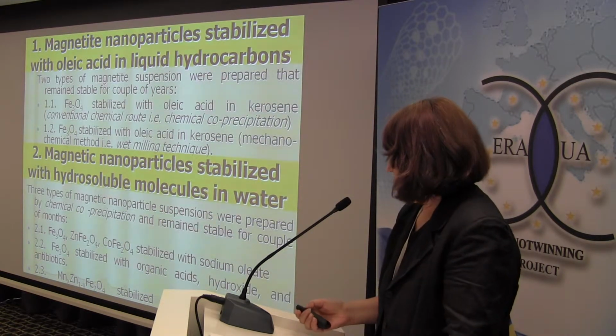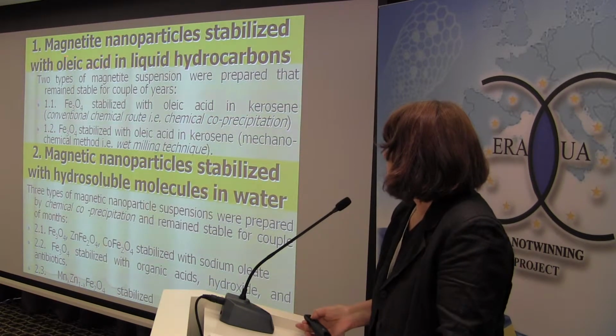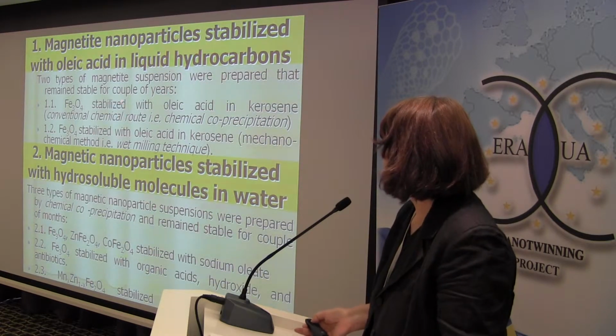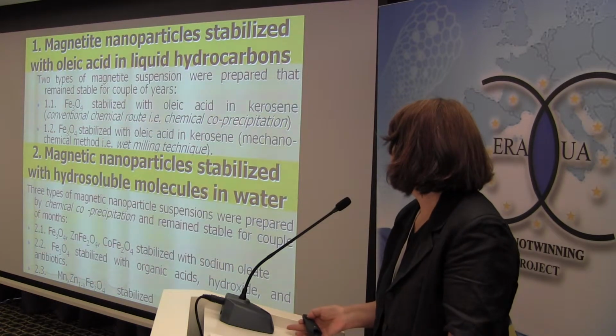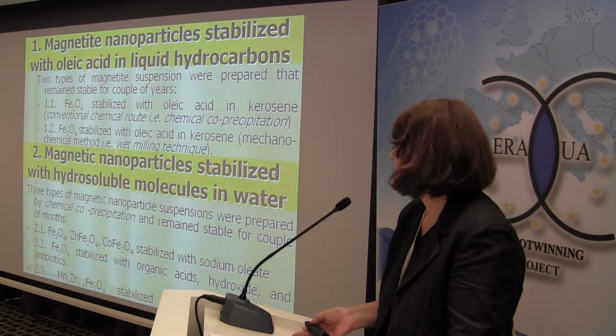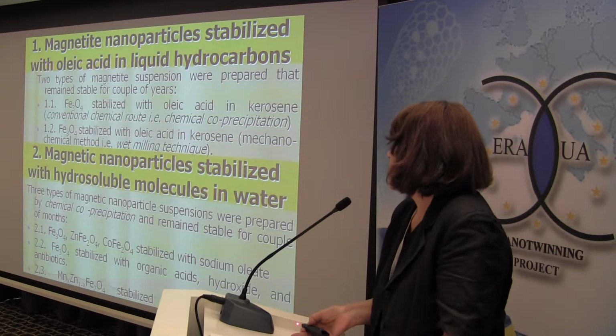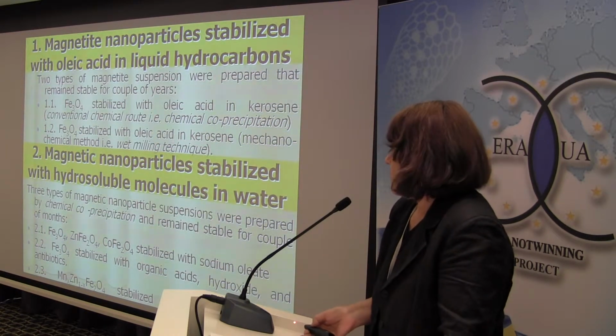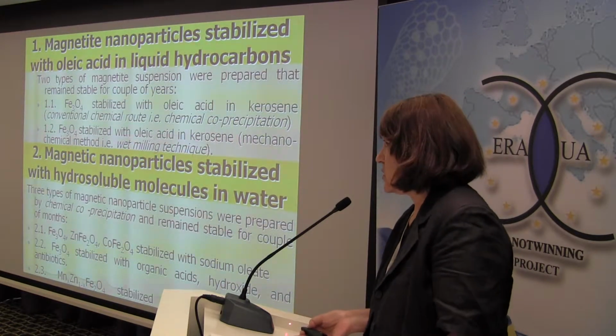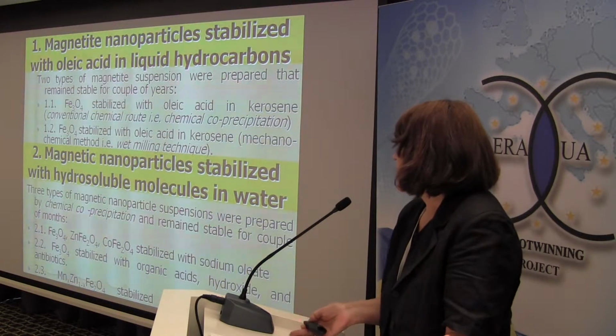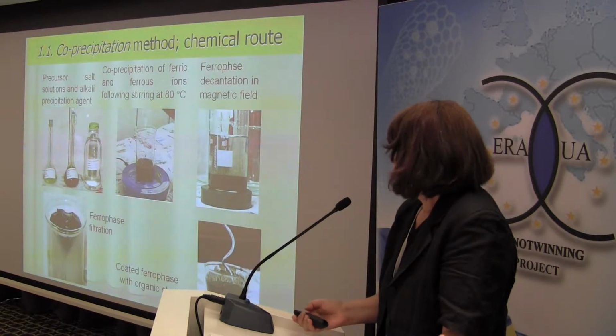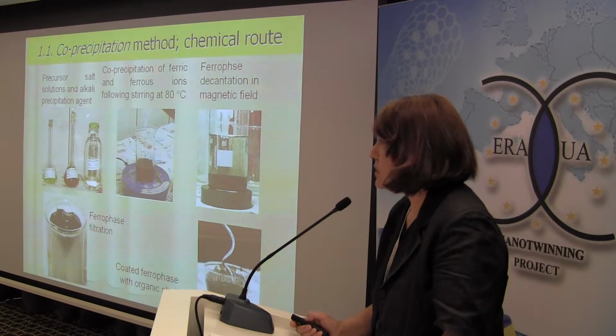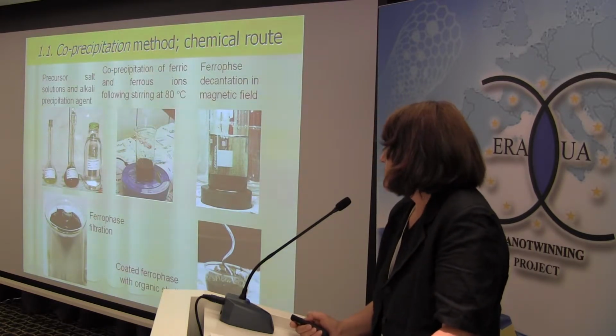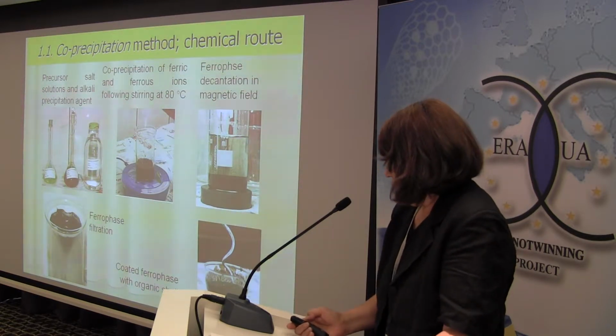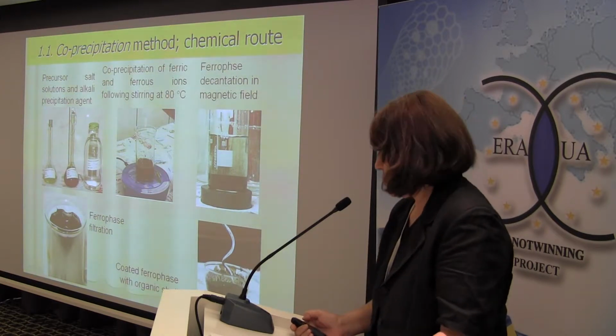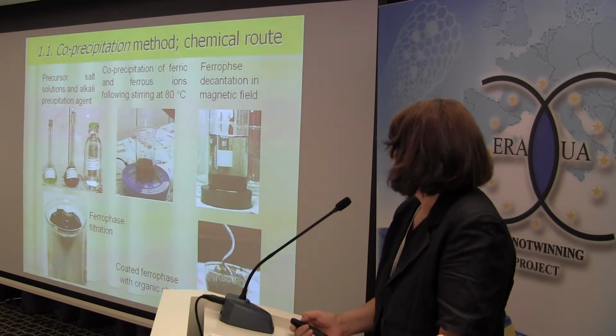We have succeeded to prepare some magnetic nanoparticles stabilized with oleic acid in liquid hydrocarbons by applying two methods: conventional chemical route or chemical coprecipitation, and then the mechanochemical method or wet milling technique. And then we have succeeded to stabilize some magnetic nanoparticles in water by chemical coprecipitation, using as the third ingredient, the coating shell of the magnetic nanoparticles, different organic molecules. The coprecipitation method is, I believe, very well known, and however, it is also still available for low cost and still leading to a rather good distribution histogram for the diameter of the particles.